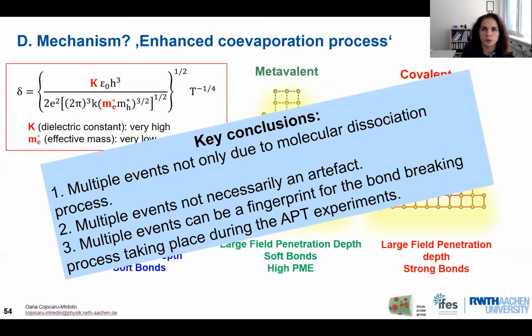So the key conclusions for this fourth part are the following. The multiple events are not only due to the molecular dissociation process. We have seen that some other processes can explain the formation of multiple events. Also, multiple events are not necessarily an artifact and can really be a fingerprint for the bond-breaking behavior during the atom probe experiments. So we have also seen that multiple events can explain this enhanced coevaporation process which takes place for the metavalent compounds.